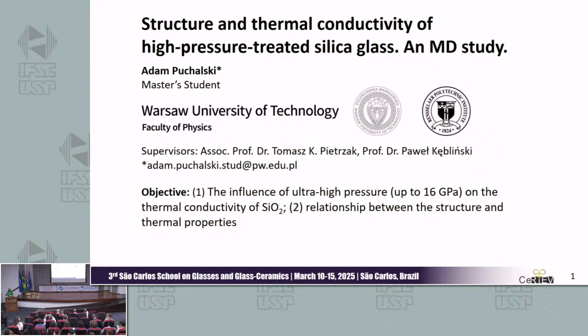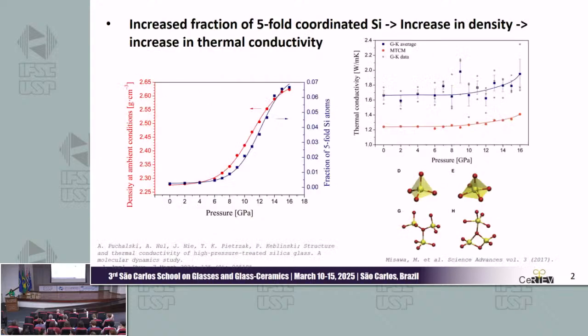The objective of my study is to study what happens in glass when we apply ultra-high pressure, up to 16 gigapascals, on the thermal conductivity. And the second objective is to study the structure and see how this structure influences the change in thermal properties. We can see that when we press the glass and then relax it, a fraction of 5-fold coordinated silicon atoms in the structure increases.